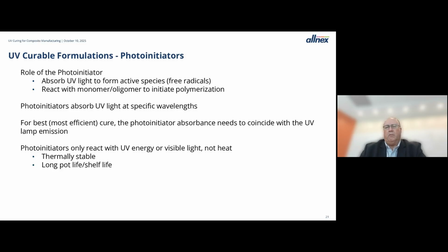And finally, we get to the role of photoinitiator, and we're going to spend a little bit of time here because it is critical to the performance of a UV system. Again, the role of the photoinitiator is to absorb the UV light or UV energy to form an active species that then reacts with the monomers or oligomers to initiate polymerization. Photoinitiators absorb at specific wavelengths, and you want to try to match the absorbance of the photoinitiator with the emission of the UV lamp. That will provide the most efficient cure.